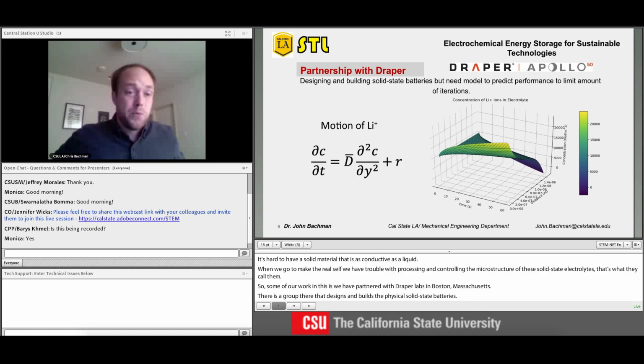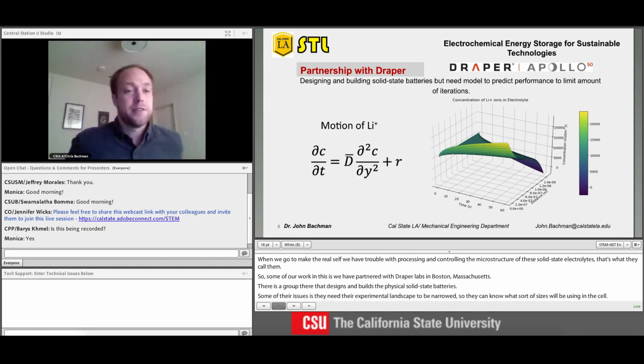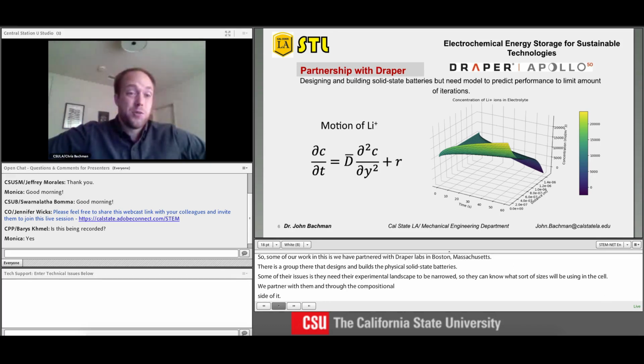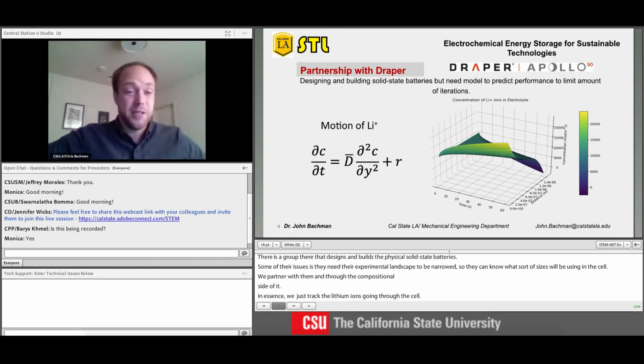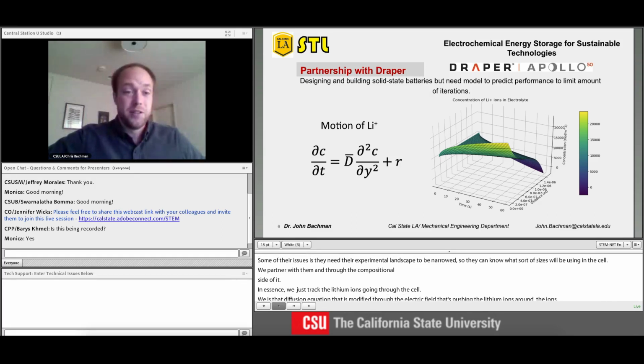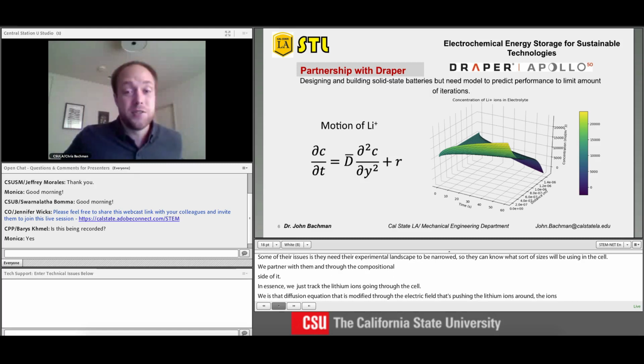So we, in essence, just track the lithium ions going through the cell. And we do that using a common diffusion equation that's modified to account for things like the electric field pushing the lithium ions around, and that the ions can merge together and go away. So you have a modified diffusion equation where we track the motion of the lithium ions in the cell. And so this is, for example, the concentration of lithium ions in the electrolyte while the cell is discharging.